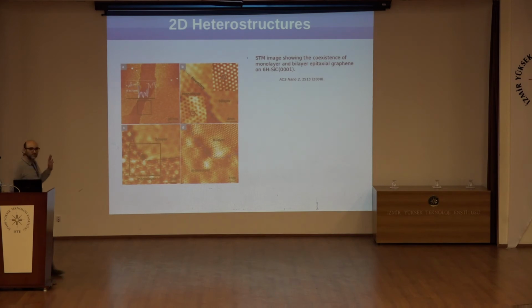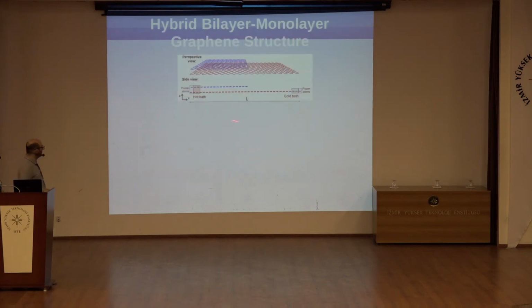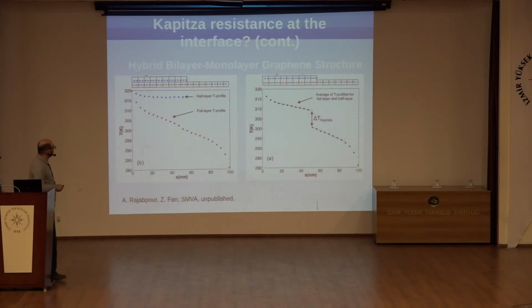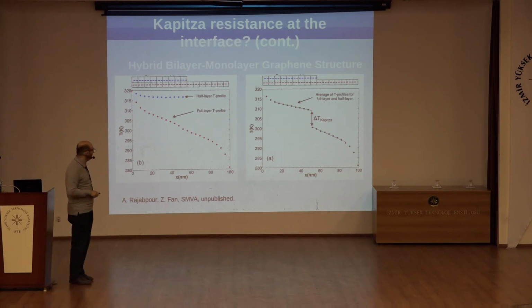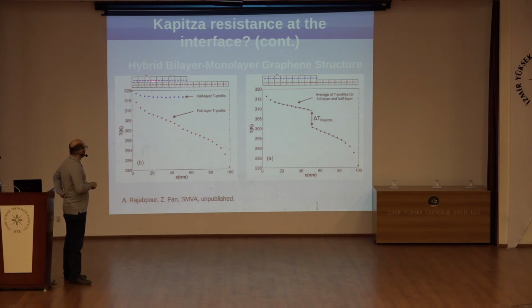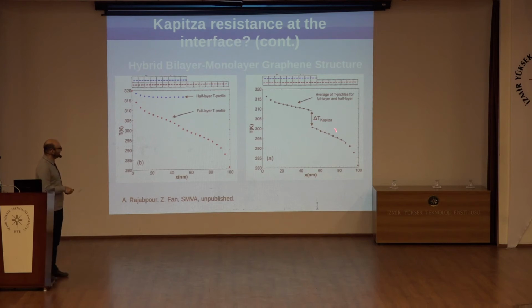To understand more precisely what is going on inside the layered media, we also studied 2D heterostructures, and as is seen here, we have a combination of bilayer, monolayer graphene, and it is possible to consider what is going on in this kind of system, and how much heat transports through the lower sheet and how much through the upper. We studied this by molecular dynamics simulation, and as is seen, it is an interesting temperature profile. It is one sort of measurement for temperature profile inside the system, and the second one.